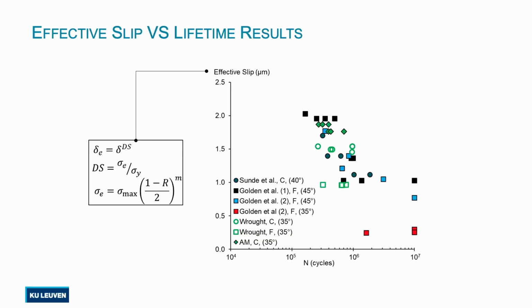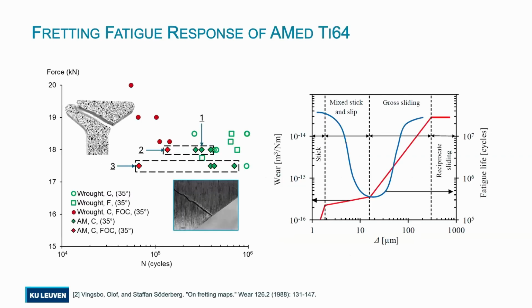And in this case, we see that there's a good agreement, except a couple of tests that they did at Purdue University, which were run out actually, and they did not provide a lot of information about their tests. So let's focus on the AM part.